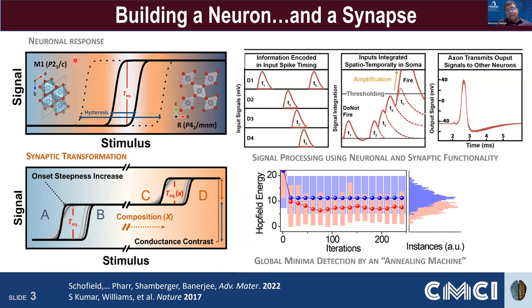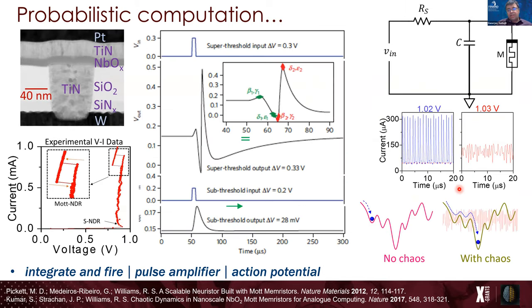And then ideally we'd like not just a neuron, we'd like to also build a synapse. And this involves taking a neuronal material, applying a certain distinctive stimulus and moving it from one part of this so that you can access a second nonlinear regime. And this can often be facilitated by something like ionic liquid gating, oxygen vacancies, and what we've done more recently, proton diffusion or lithium ion diffusion, right? So in many senses, some of these can behave like battery materials, right? And if you do this right, you can of course build out a system that does interesting computations, as was shown by my colleague, Stan Williams.